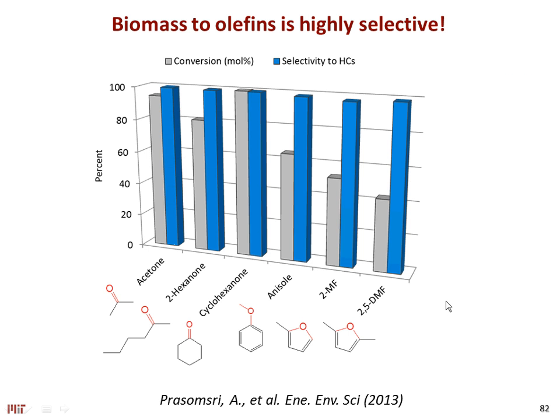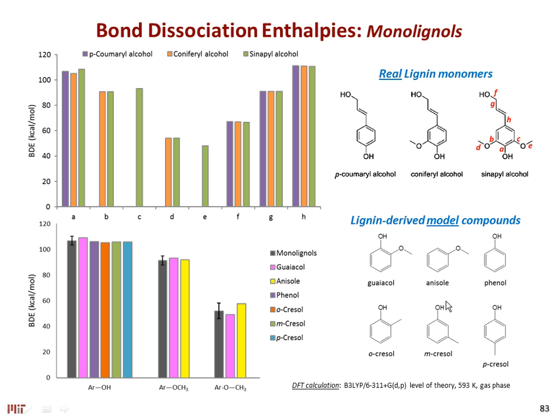So we started doing, again, our classic approach, a quick screening of different molecules. And what we found is that our selectivity to hydrocarbons was always very high with molybdenum oxide, working at hydrogen pressures of less than 1 atmosphere, right? So we would work under atmospheric conditions, low partial pressures of the oxygenate. And what we found very interesting is that the bonds that we were breaking in these molecules were not what we would expect from our bond energy analysis.